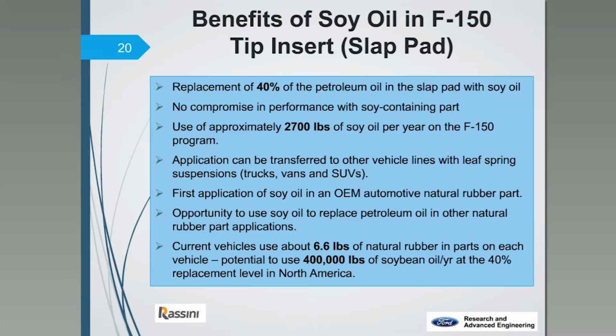The benefits of the soybean oil tip insert: 40% reduction in petroleum oil. We had no compromise in performance, and we're using, in this case on the F-150, 2,700 pounds of soybean oil, but we anticipate, since this is the first part, being able to now transfer this knowledge to many, many other parts. And as I mentioned previously in this presentation, we use about 6.6 pounds of natural rubber per vehicle. And so if we replace 40% of the petroleum oil with soybean oil, we're up to about 400,000 pounds of soybean oil per year. So that's our goal.